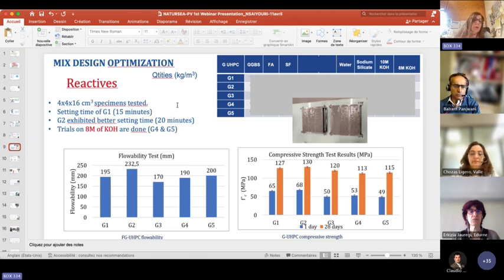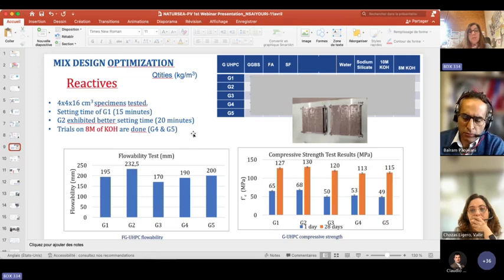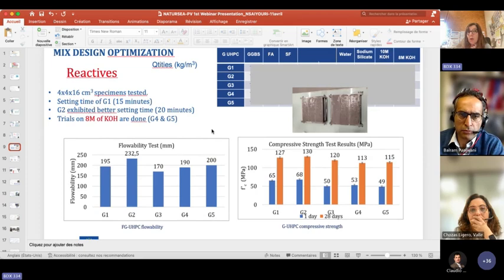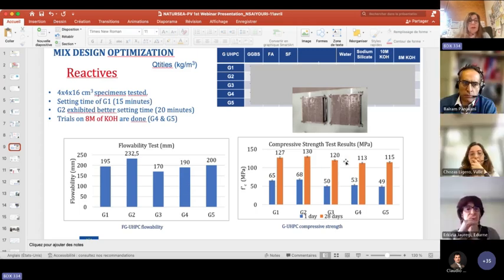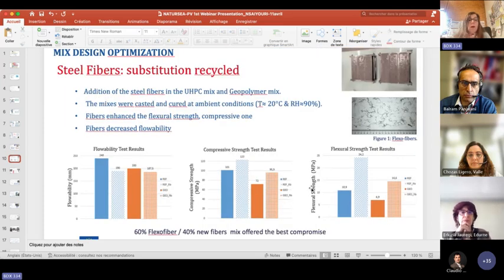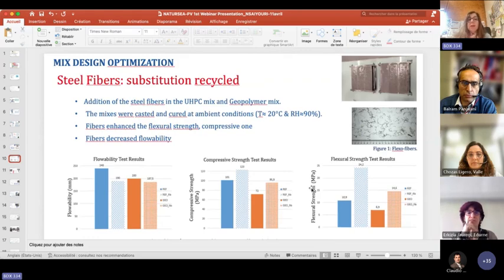We usually use specimens of 4x4x16 cubic centimeters, and we see what is happening with the sodium silicate. We tried also, in these results, potassium silicate, because it's giving more interesting results. The criteria are always flowability and compressive strength, and this allows us to choose some mixes in that kind of set of tests. As you see, we are not far from our target, our goal. The 1 day and the 28 days are quite close to what we decided.